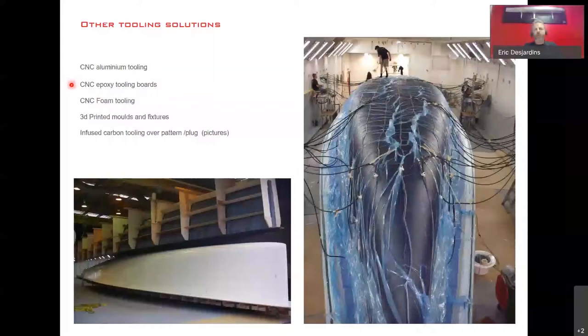You can do epoxy tooling boards, similar, that will be reserved for smaller parts like rudders. Same with aluminum tooling. You'll keep that for the very critical parts that need extreme consolidation, maybe up to 4 bars of consolidation. If you're not using temperature sensitive material, you can use a foam tooling for hand laminating at ambient temperature. And in the last 5 to 10 years, we started using small 3D printed molds. Very, very humble application. The molds are not very big, but that's definitely used more and more.